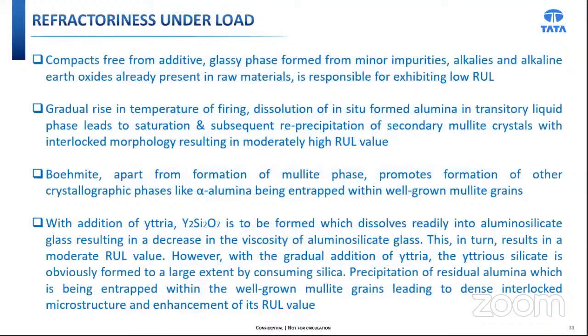Now coming to the refractoriness under load. With the gradual rise in firing temperature from 1400 degrees by 50 to 75 degrees centigrade, dissolution of in situ formed alumina in the transitory liquid phase leads to saturation and subsequent reprecipitation of secondary mullite crystals with interlocking morphology, resulting in a moderately high RUL value. With increasing temperature and with increasing dopant content, the RUL value increases up to 1675 degrees centigrade.